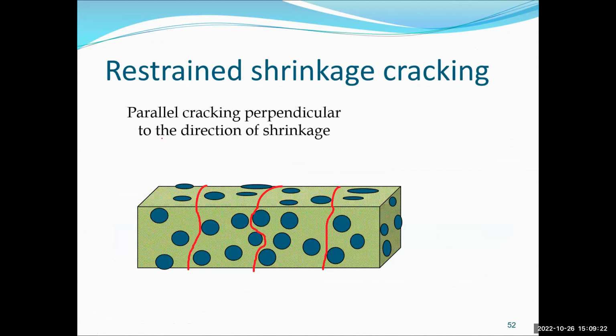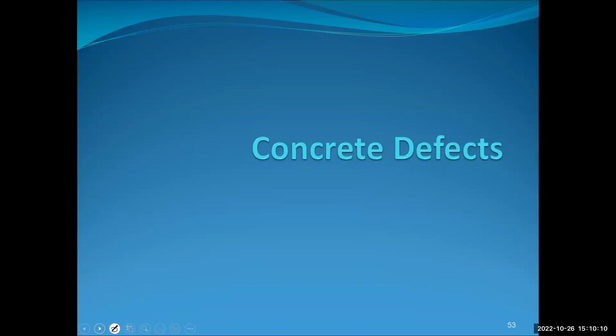Here's another way you can tell restrained shrinkage: if you see parallel cracking approximately 8 to 10 feet apart, that means you are not providing the concrete the freedom to move. If you restrain it, you're going to start creating parallel cracks approximately 8 feet apart. That's why when we cast a slab on grade, we put plastic sheets on top of the gravel. These plastic sheets will minimize the contact and the bonding with the aggregate.